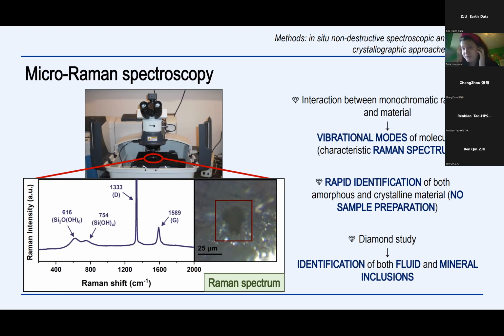For these reasons, we use micro-Raman spectroscopy in diamond inclusion study as a first step for the identification of both fluid and mineral inclusions that diamonds can contain within them. If we analyze the Raman spectrum of inclusions and also the Raman spectrum of diamonds, we can also obtain other kinds of information. But as the first step, this technique is used for the identification of the material.